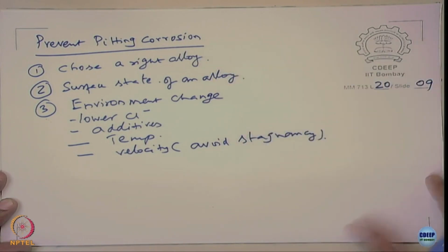And for that you also have tests like critical pitting temperatures, EPIT values. Please again notice these are all rankings of the materials. I do not think that these tests are going to give you any kind of life that you can predict. That is simply not possible so far for the pitting corrosion of metals. Coming back to the first aspect, that is the choice of alloy, and when it comes to stainless steels, you know that you want to increase the pitting resistance. One way to look at it is the composition, which is the pitting resistance equivalent number. If it goes high, then the pitting resistance increases.